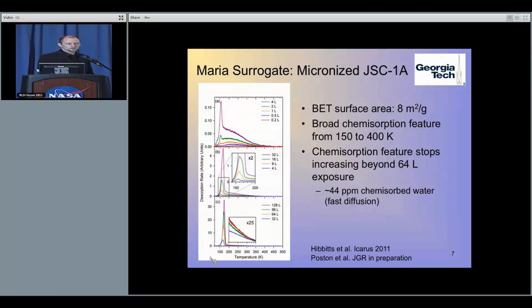So we then exposed the samples to these water doses, these units are just a unit of exposure, and we didn't see any evidence of the hydroxyls coming back, which is consistent with the literature where you have to leave the samples out in the room for like a week or two before you see hydroxyls growing back in.